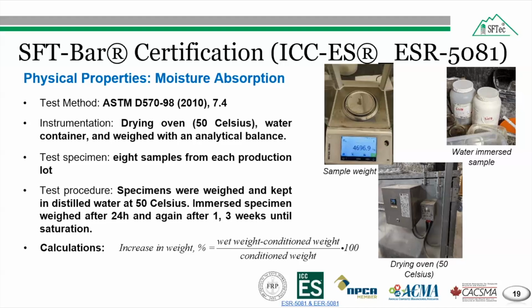The first weighing occurred after 24 hours, and then the specimens were immersed in the water again. Then we extracted and weighed them every week until we reached the saturation level. Saturation was confirmed when the increase in weight over 3 consecutive measurements was less than 1%. The water absorption at 24 hours and at saturation was calculated as the increase in weight in percentage, equal to the weight minus the condition weight, divided by the condition weight.